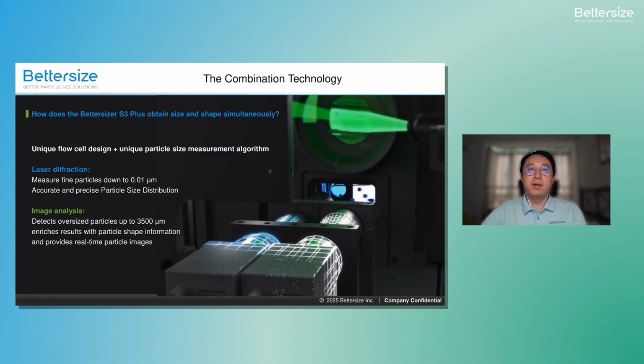As mentioned earlier, the Bettersizer S3 Plus combines laser diffraction and dynamic image analysis in one instrument. Thus, it can measure the size and shape of cement particles from 0.01 micron to 3,500 microns. Benefiting from image analysis, it has exceptional sensitivity for oversized particles. With Bettersize's patented DLOI system, the Bettersizer S3 Plus also expanded the lower limit of ultrafine particle detection. The unsurpassed resolution and its sensitivity for either ultrafine particles or oversized particles make it the most powerful size and shape analyzer for enthusiastic researchers who conduct top scientific research.